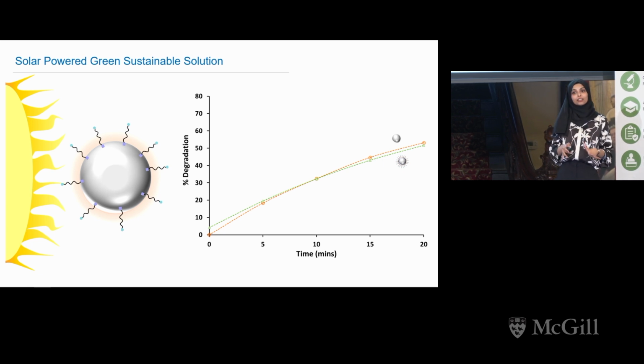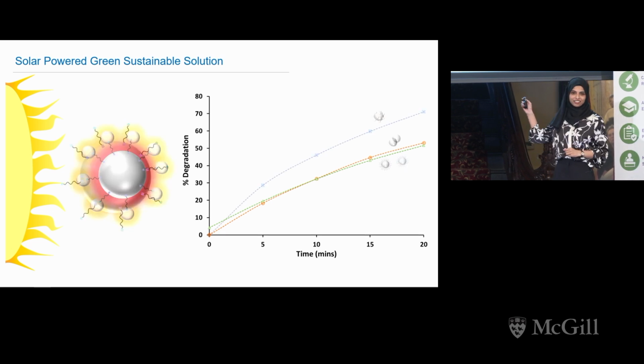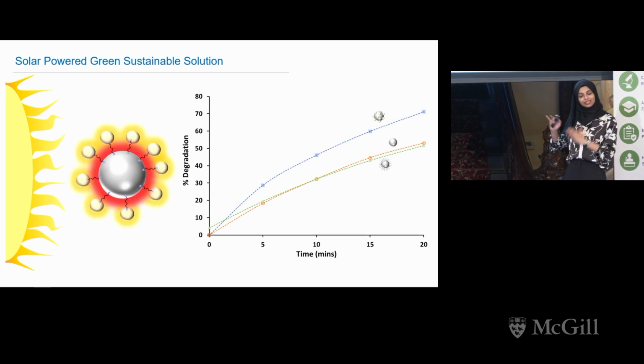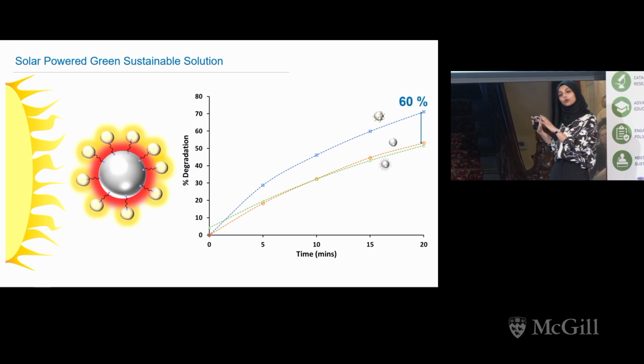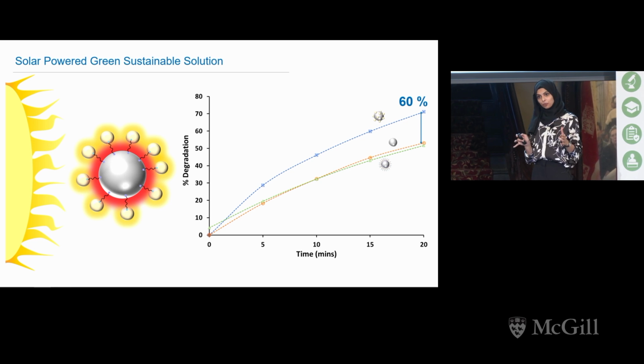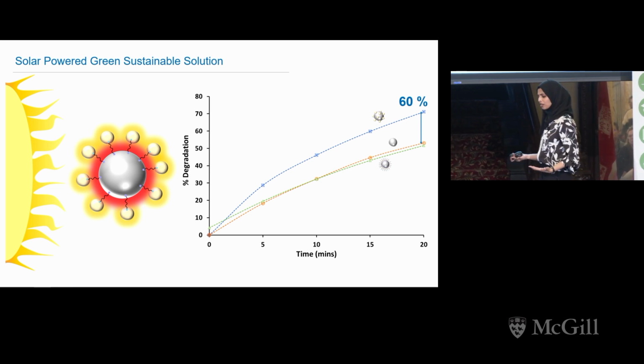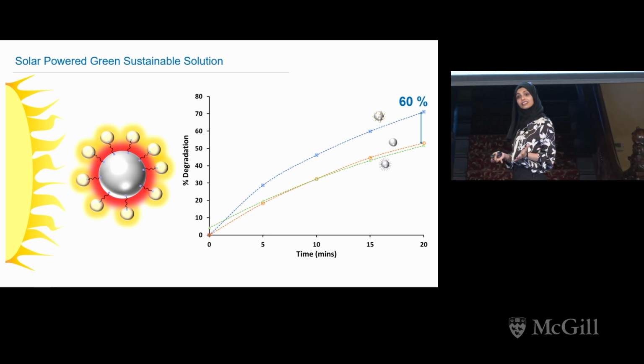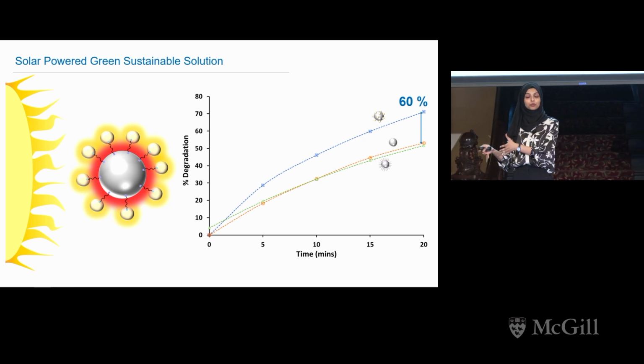And finally, the hero of my project: the light antenna, ligand, and photocatalyst combination. Here's the degradation curve. We clearly see an enhancement in the degradation performance, about 60%. This can solely be attributed to these light antenna nanoparticles, meaning they were successful in concentrating the light energy and transferring it to the photocatalyst.